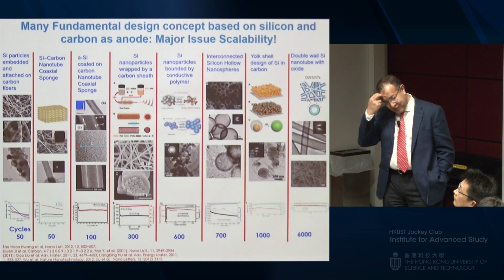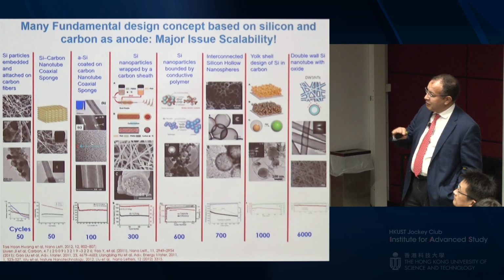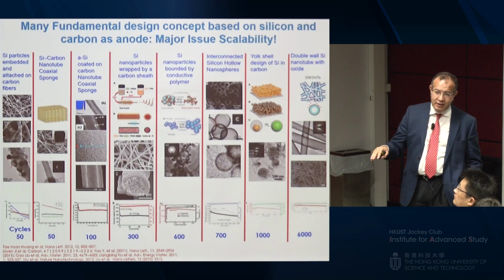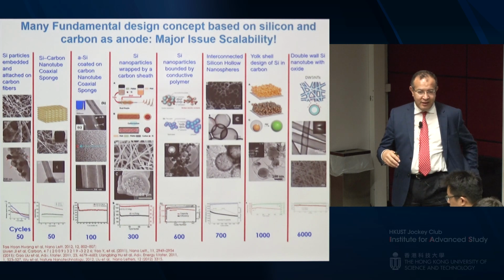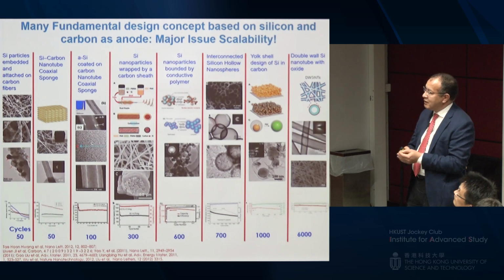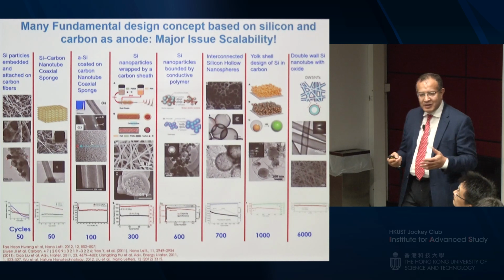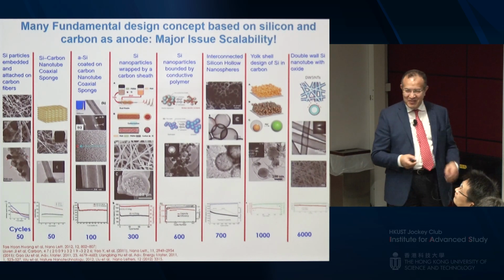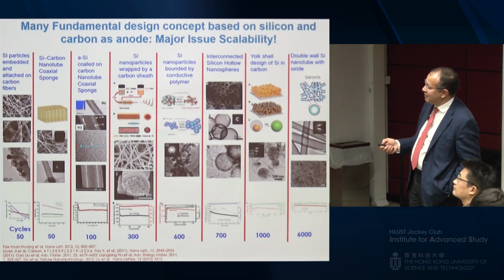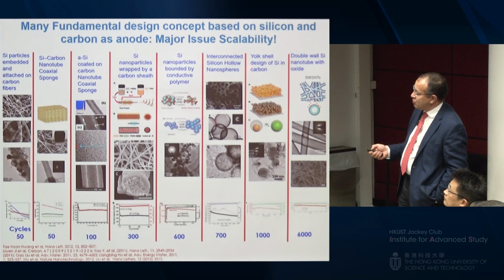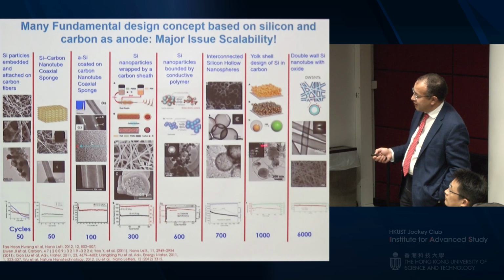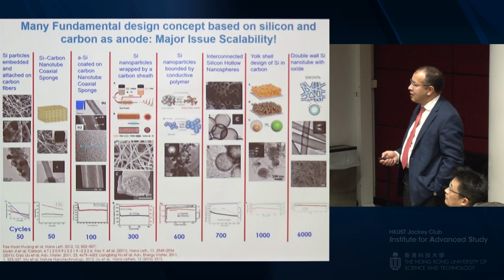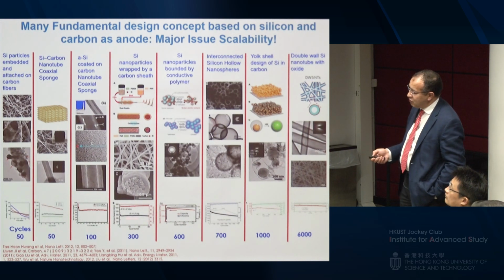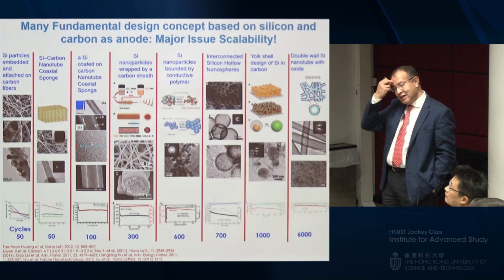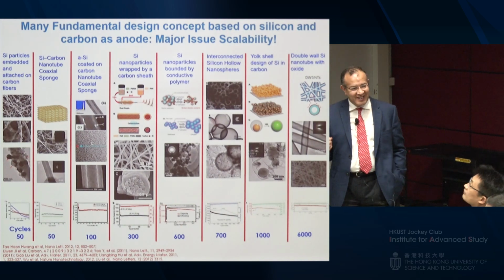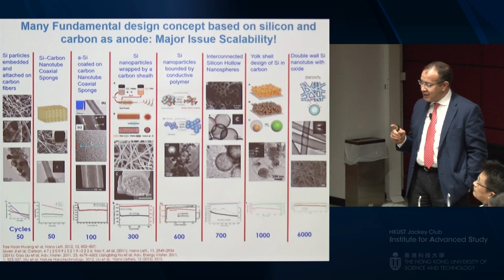Much work has been done in the literature, where basically what they do is incorporate silicon in a carbon matrix to keep conductivity. They put it in carbon fiber, nanotubes. My colleagues at Stanford use the yolk-shell type, where they incorporate the silicon inside the carbon spheres and so on. But all of these show very good results. I'm not sure about these results because the loading is very small. It's like using shallow charge and discharge. So one has to be very careful.